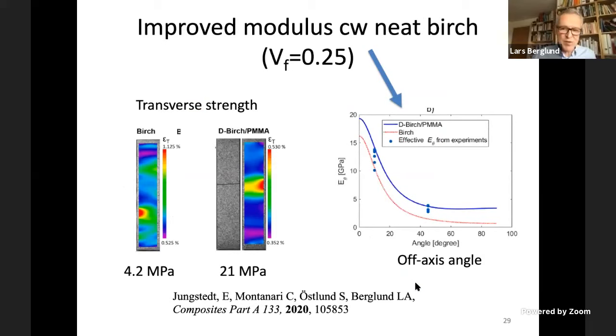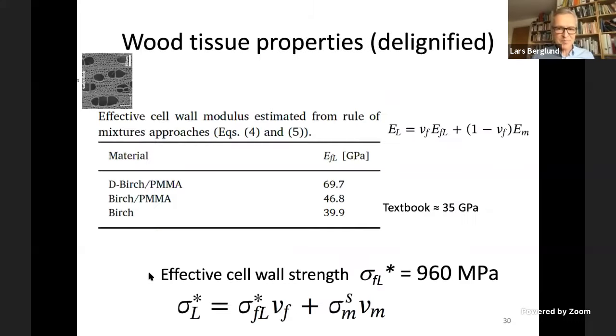In the transverse direction, we actually see substantial improvement. So for the composite, we have a strength of 20 megapascal, and for neat birch, it's only 4 megapascal. It's simply a porous material where we initiate failure at very low strains.